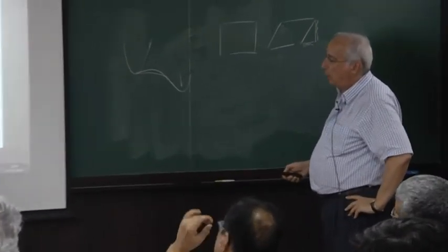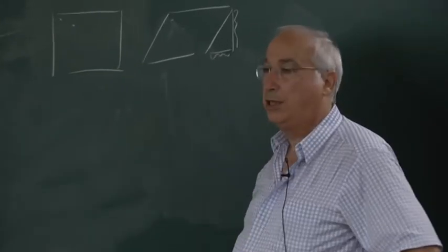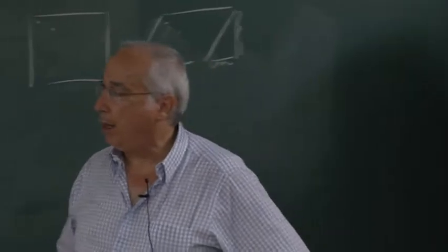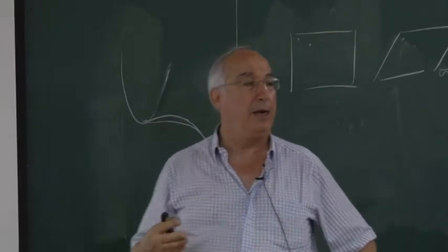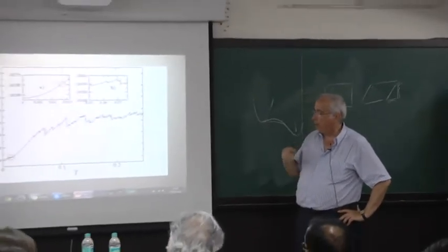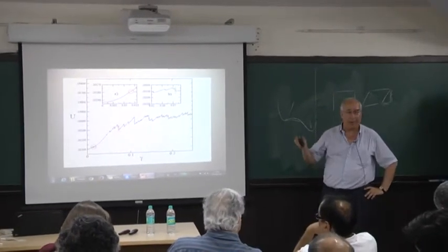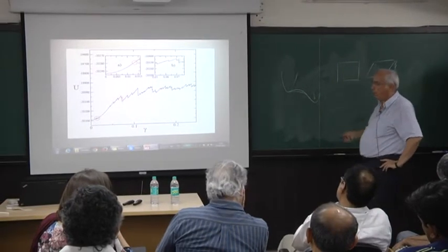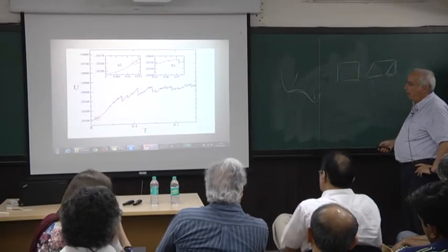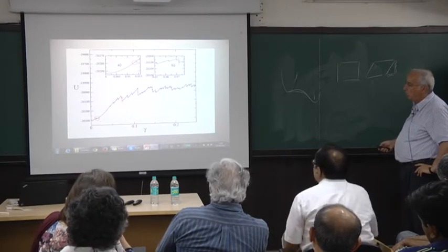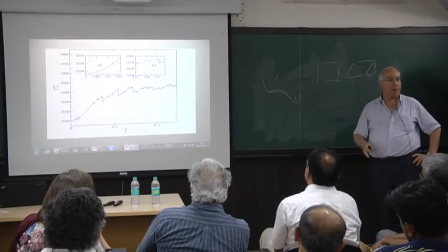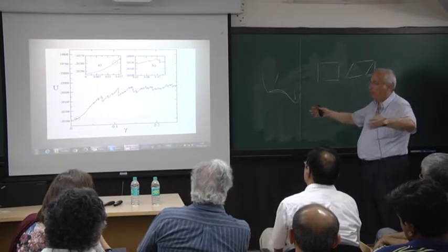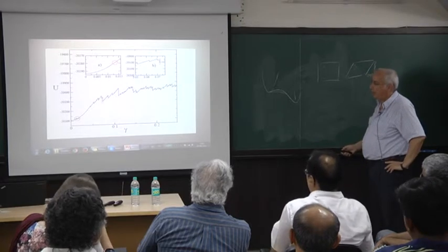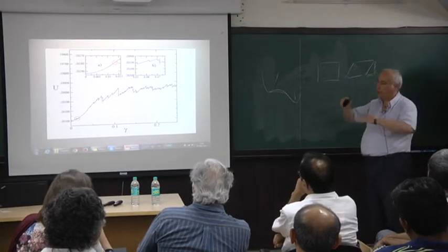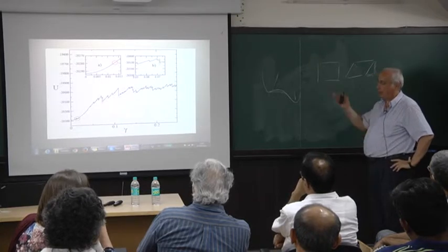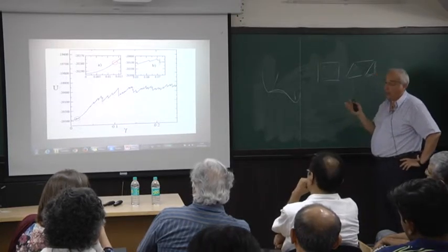At some point, when you go to a large gamma, you begin to get large drops. And what is large? Again, system size dependence. Now you look at these as a function of system size. They are sublinear. They are subextensive in the system size, but they depend on the system size. They go like N, the number of particles, to some exponent smaller than one. And these large events are what I want to understand, because these large events, I'm going to argue, are system spanning. Of course, they have to be system spanning if they grow with the system size. And these are the origin, or the clues, if you want, to these interesting instabilities that we started with, the shear banding, even though it's not yet shear banding.